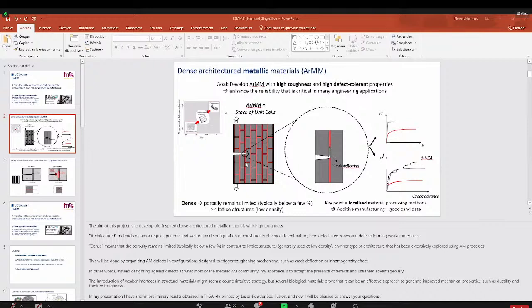It's really not like a lattice or such things that usually people are talking about when using the word architectured materials. And so the idea is to organize the defects associated with the LPBF process in such a way to organize them in interfaces, and this will hopefully generate a mechanism of improving the toughness, such as crack deflection, inhomogeneity effect, and so on.